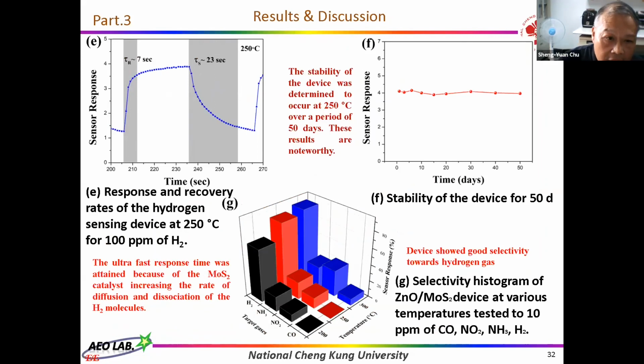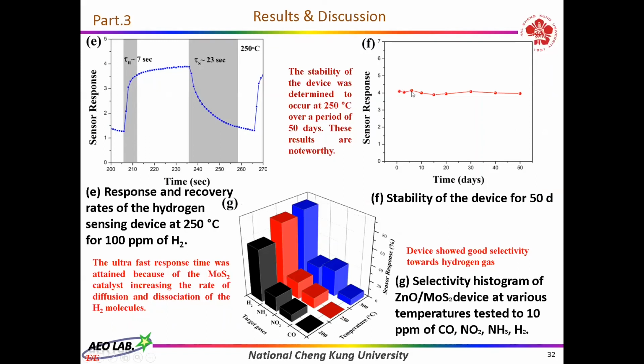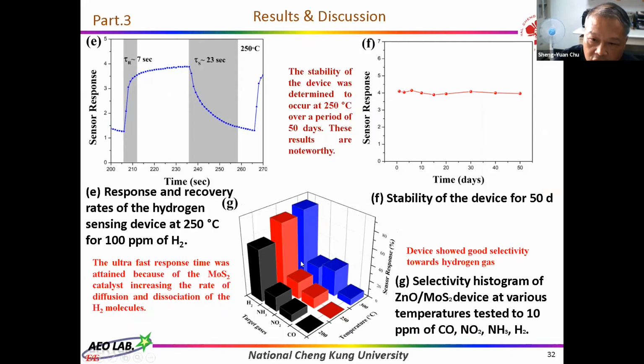And in this figure, the response time is about 7 seconds, and the recovery is 23 seconds. And the ultrafast response time was attained because the MoS2 catalyst increased the rate of diffusion and dissociation of the hydrogen molecules. And the stability can be up to 50 days. And also, it shows good selectivity towards hydrogen gas.